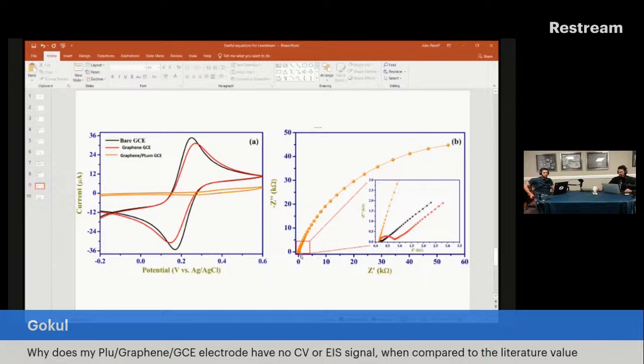But he zooms in on this little region in the Nyquist plot, and he shows that, okay, for the bare glassy carbon electrode and for the graphene modified glassy carbon electrode, he gets these normal Nyquist plots. I think it's hard to see here, but you do get a small semicircle with a diffusional tail, what you would normally expect when looking at ferrocyanide. But in the case of this graphene with plum, I'm just going to call it plum, he doesn't see that. He does not see the semicircle, and you just get what you may describe as a diffusional tail just going straight up. But I don't know if I'd call it a diffusional tail, especially when we have the CV data to confirm that there's really very little to no current response here.